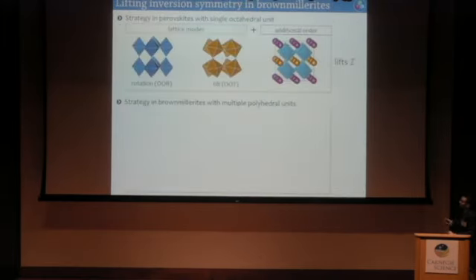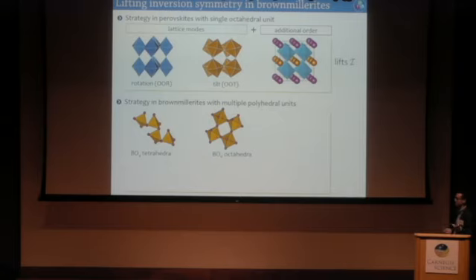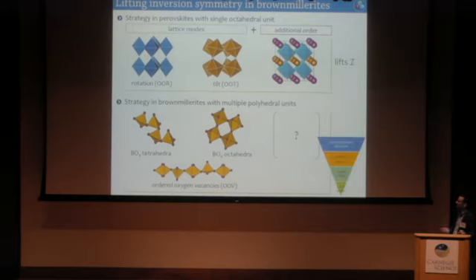Okay, so in perovskite, we can lift inversion symmetry through a combination of rotation and tilt, chemical order. In brownmillerite, we're going to try the same thing, except it's not really tilting. It's just a combination of static structural units, tetrahedra and octahedra, which have chain-like structures like this, ordered oxygen vacancies. And we're going to have to add some other feature to lift inversion symmetry, or to deterministically lift inversion symmetry. And that, just like in perovskite or these superlattices, will be chemical order.